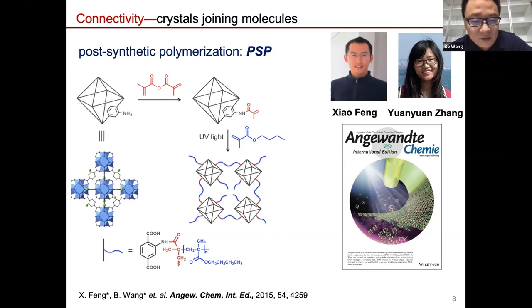Eventually it copolymerized to give you a self-supported membrane. And the good thing here is those particles are covalently bonded to the polymer chain, so it's rather anchored in space. And when you have such a membrane, compared to the traditional MMM, or mixed matrix membrane, this membrane is rather robust. The particles cannot move easily in the structure. So that gives you a rather robust membrane for different gas phase or liquid phase separation.